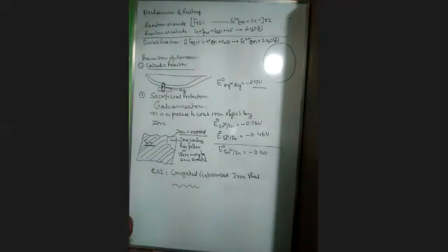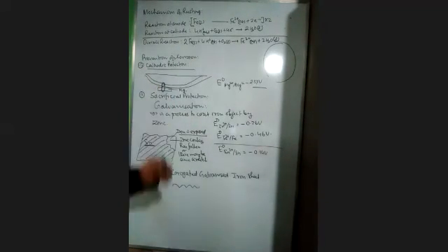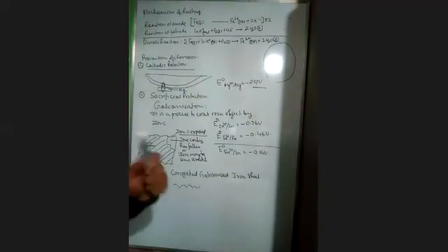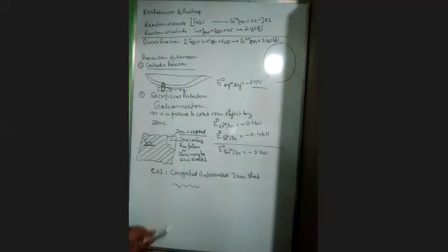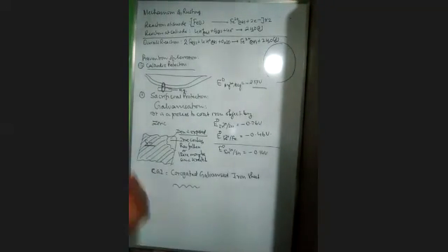All right. So now, after a few months, the magnesium will corrode and will disappear. Then in that case, again rusting is there. So when you put this underground cable, now with the GPS system, we can locate where those magnesium slabs are. So the divers are sent along with a magnesium slab, and they go and tie a fresh one. So years after years, this cable can be used and there will not be any rusting.